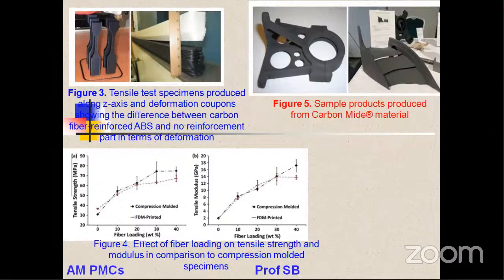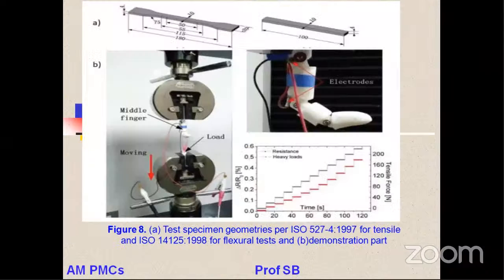And these are the 3D printed tensile specimens and some components, and you can see the tensile strength versus fiber loading and also modulus for the fiber reinforced composites given here. With increase in fiber loading, you can see strength is enhanced up to almost 40 weight percent. If you look at 30 to 40 weight percent, the strength enhancement or even modulus enhancement is slightly on the higher side, whereas strength is almost optimized. So maybe 30 to 35 weight percent of fibers you can think of as the effective reinforcement with the epoxy material or ABS material for the development of composites with optimum properties using 3D printing.